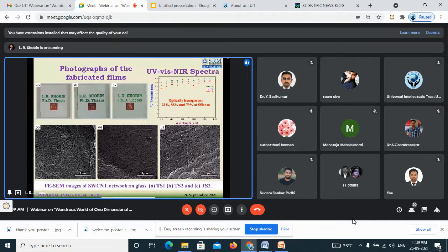And these films are tested in UV-Vis-NIR spectra also. If you test it, they are transparent in UV and NIR region also. These films are good at transparency. What you will see in the microscope? So far the film is transparent. Once you increase the number of coatings, the transparency is decreased.